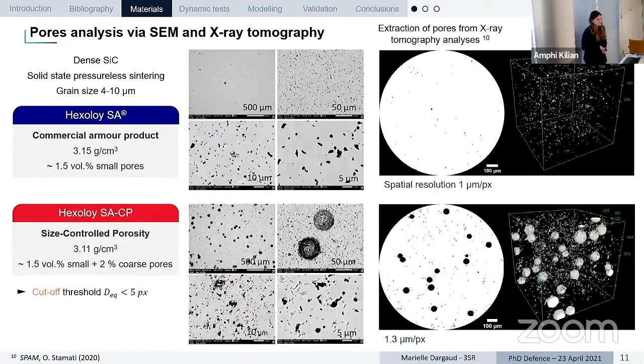Now, we've done some tomography analysis on these two materials. Here you have some images of the post-processing of tomography 3D images, where we extract, from a gray level thresholding, only the porosity, which are the main defects present in this type of material. To resolve these different defects, we have to reach high spatial resolution for the tomography scan. So we have very small samples to be analyzed from tomography.